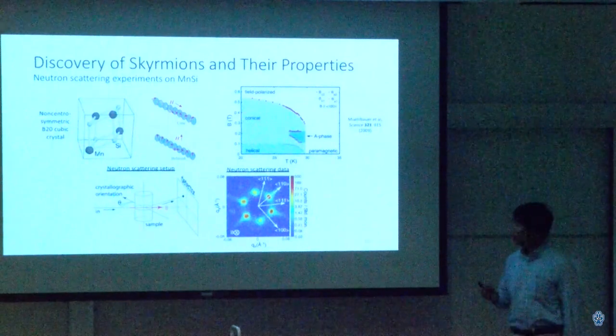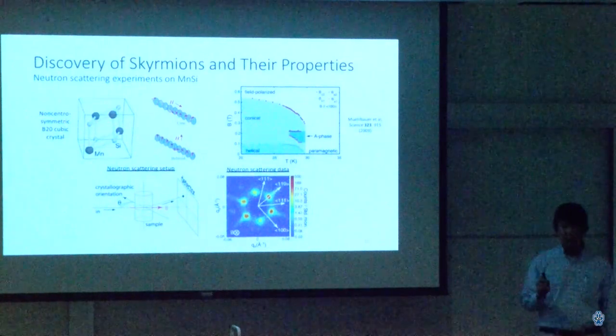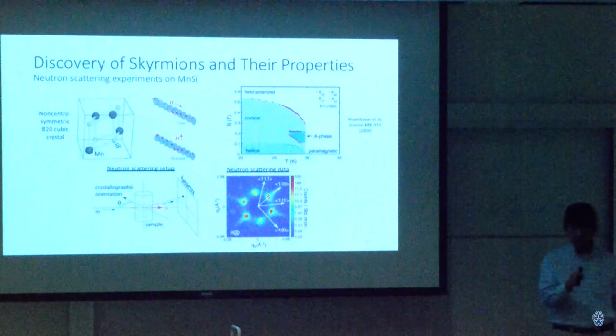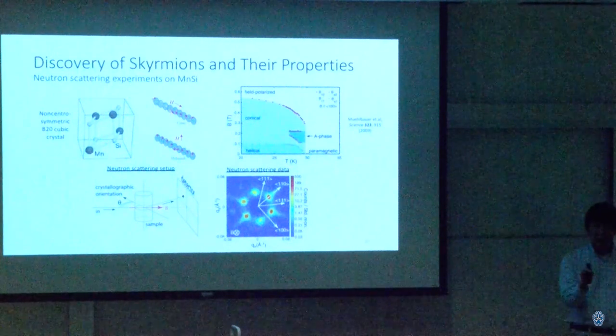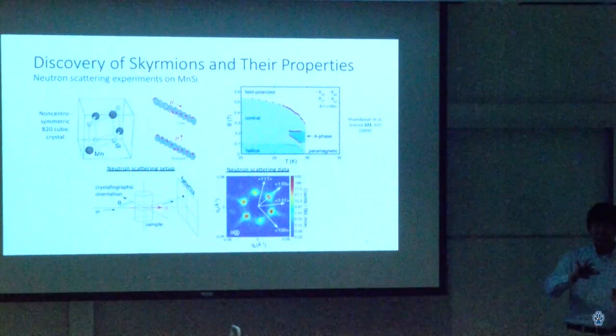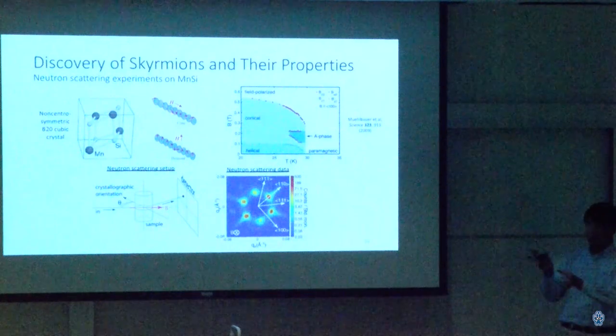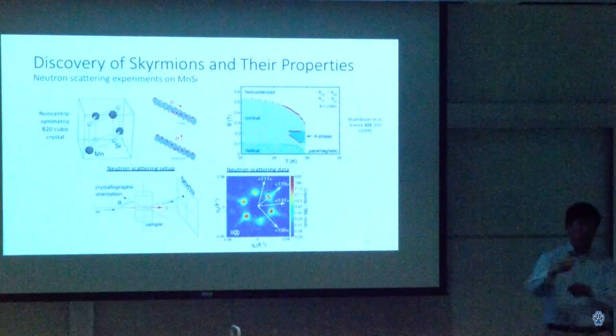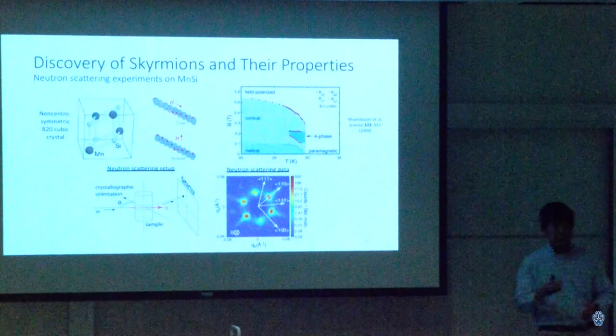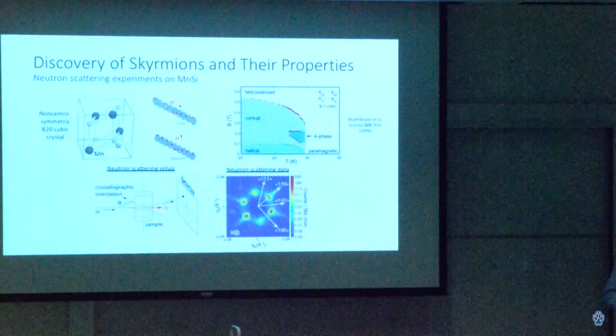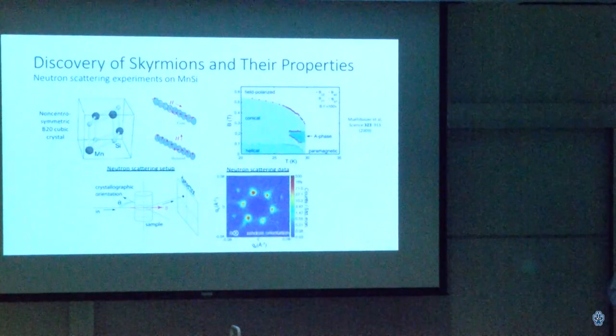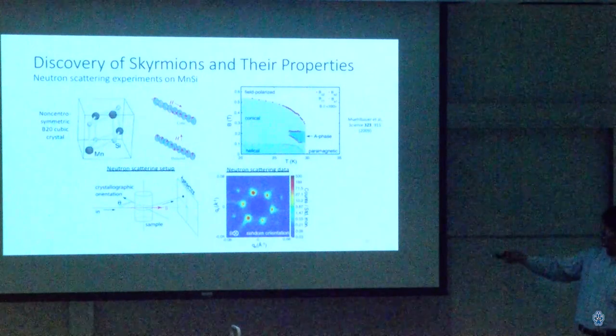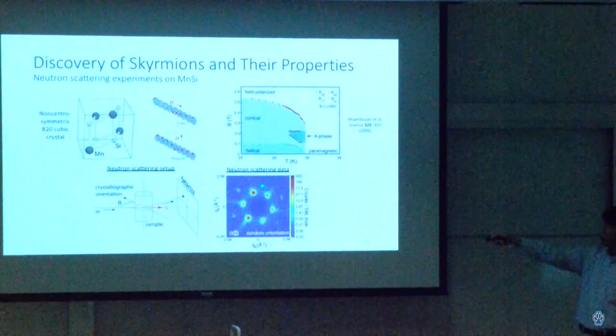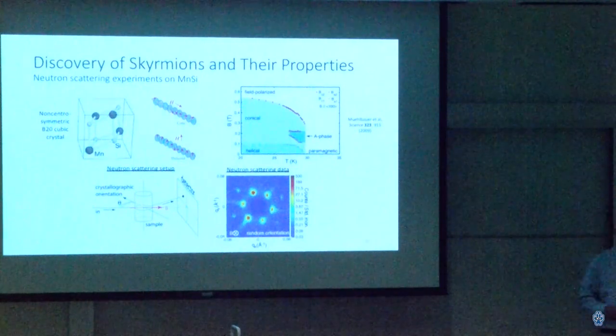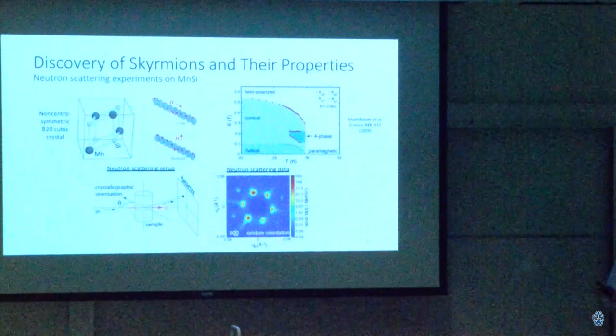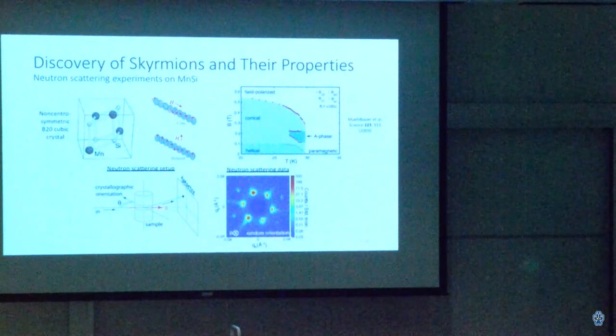One of the predictions from skyrmion theory is that if you point your magnetic field in some random direction, the skyrmions will also form and conform to the direction of the magnetic field that you point. It doesn't have to go along special directions, in other words. So they pointed their magnetic field in some random direction, and they still saw the same pattern. So that's interesting. The spin texture changed.